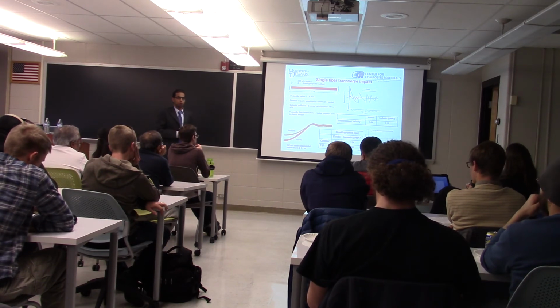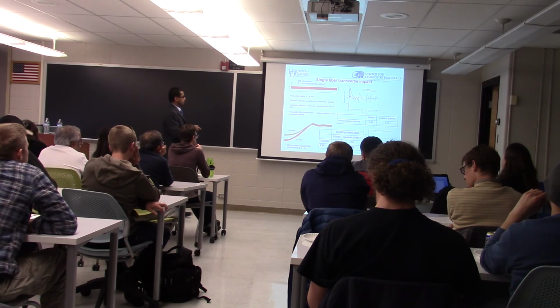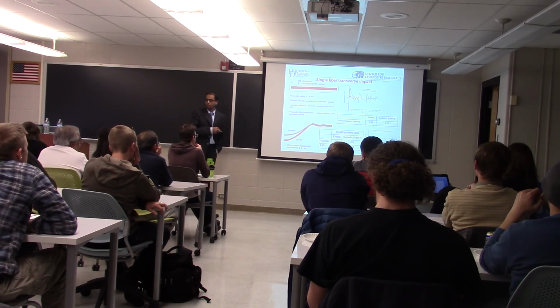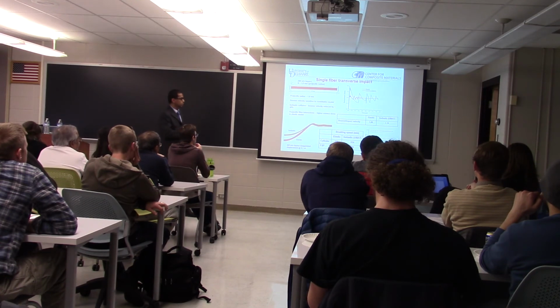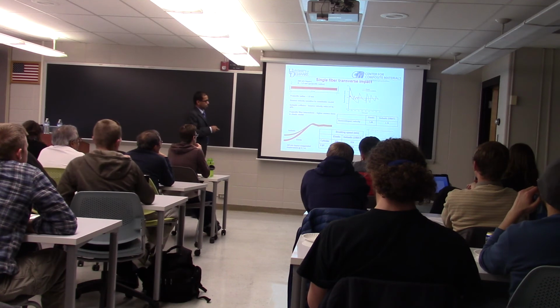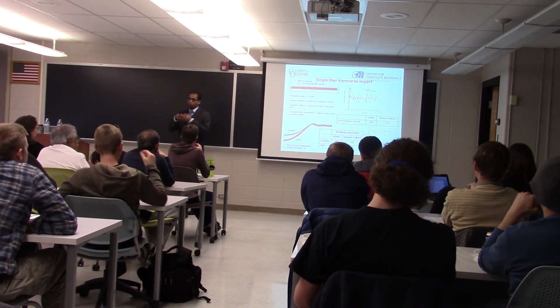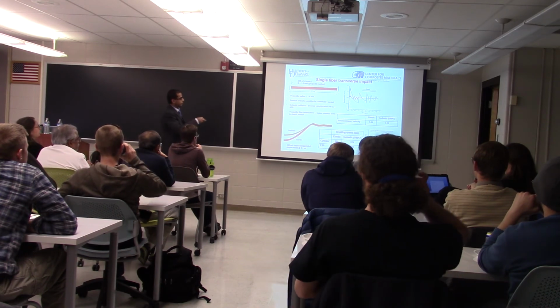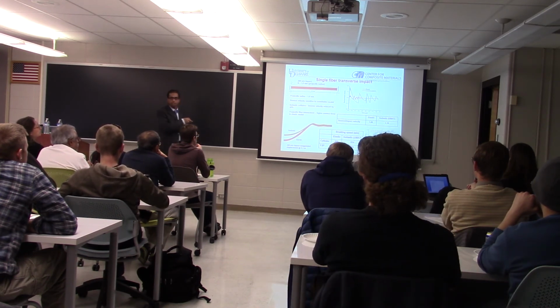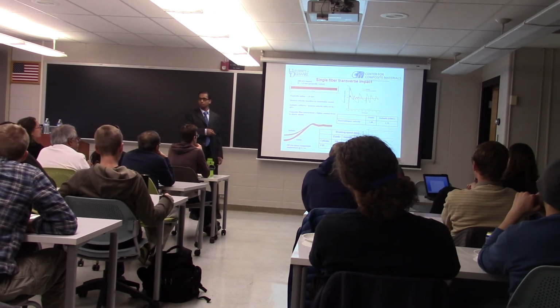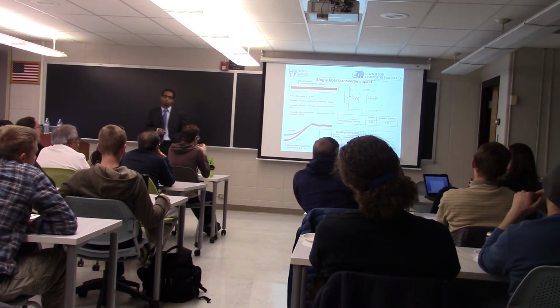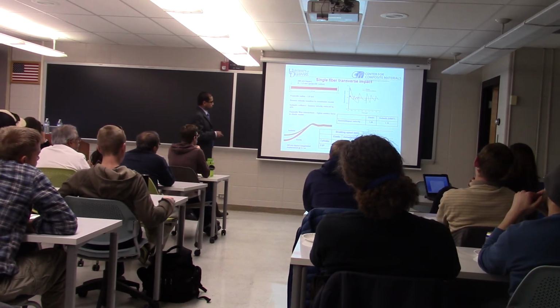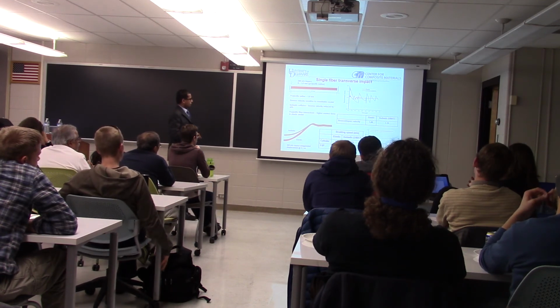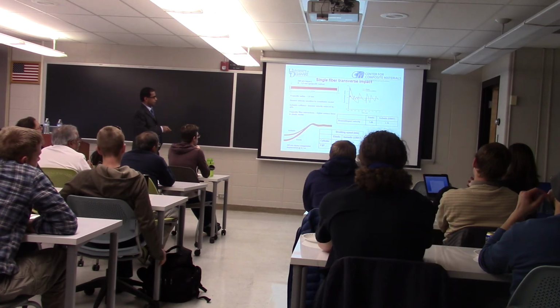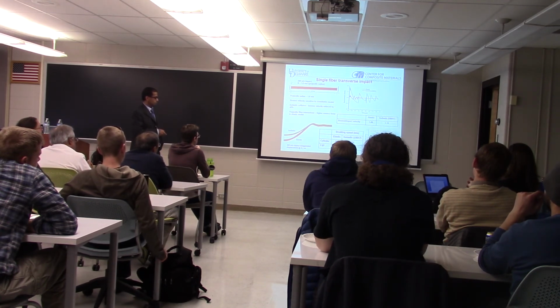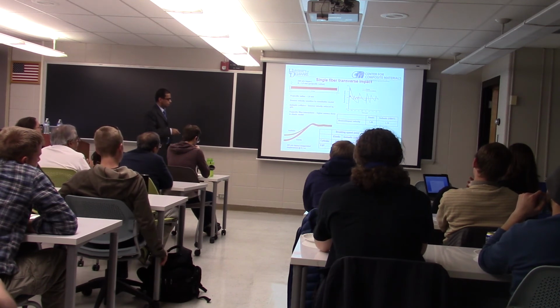Now we have the material model for nonlinear behavior of the fiber. The next step is we want to understand how that affects the impact response. So we went back and studied this impact of the fiber using the nonlinear model. In the elastic case, we saw that the fiber bounces in front of the projectile. The projectile repeatedly interacts with the fiber, resulting in a series of bounces like this. Whereas in the case of the inelastic material, this effect is significantly diminished due to the plastic dissipation of the inelastic behavior. So that's what is shown here. And also the curvature predicted by the inelastic model is much smaller compared to the elastic model. Therefore the breaking speeds predicted by the inelastic model are higher compared to an elastic case.